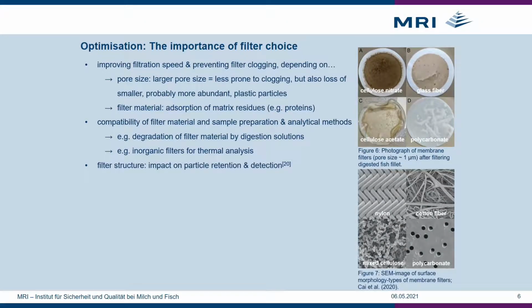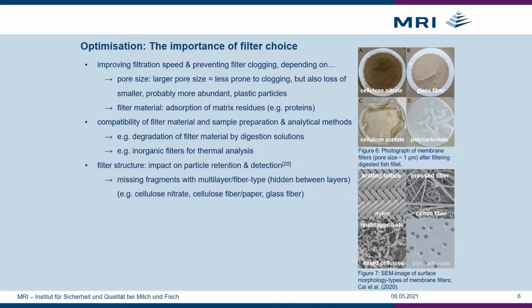However, not only the chemical composition of the filter material, but also the filter structure has a significant impact on particle isolation. Multi-layer or fiber-type filters, such as the often used glass fiber filters, might lead to an underestimation of particles when they are hidden in the depth of the filter.